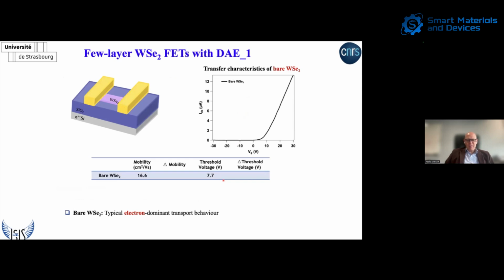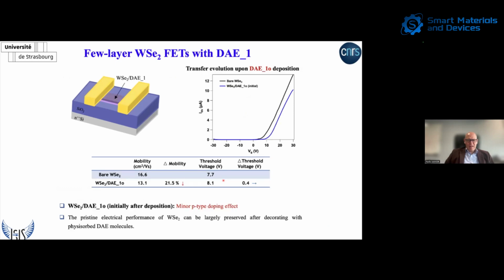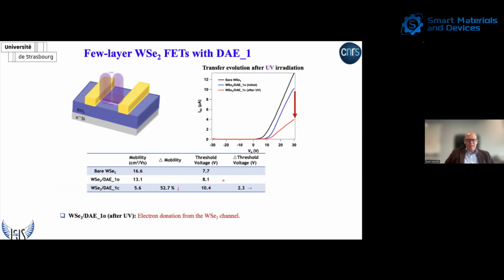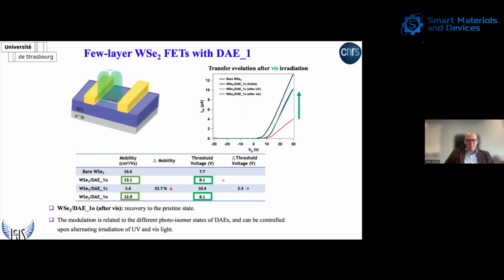Now, we start from an unoptimized device of bare tungsten diselenide, with a mobility of 16 centimeters squared per volt per second. We physisorb the diarylethene in the open state, which is the one that is not trapping. And so we have a reduction of the mobility that is quite minor, about 20%. Then at this point, we irradiate in situ with UV light. So we close the diarylethene, and we have a mobility decrease of 50%. And now, because the closed diarylethene acts as a trap, we can irradiate with visible light to reopen it, and you can observe that we fully recover our initial mobility of 13 centimeters squared per volt per second, and the threshold voltage is back to the initial value, so we are undoping our device.